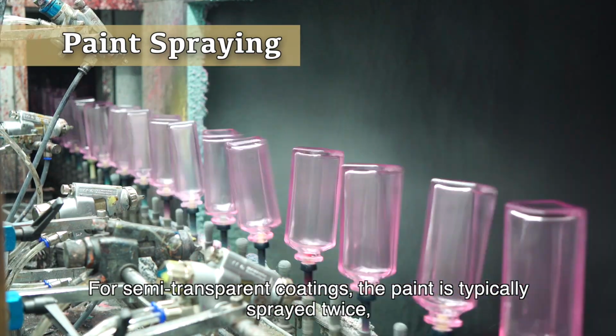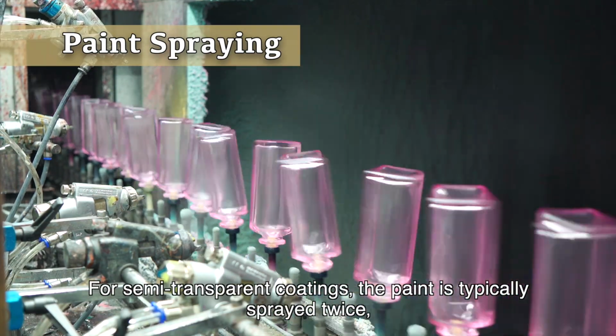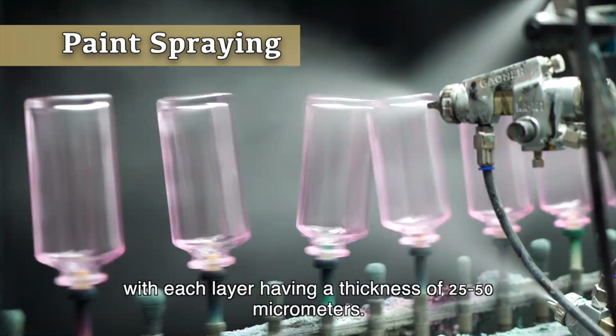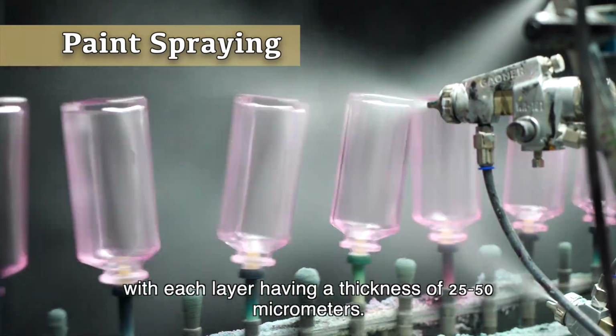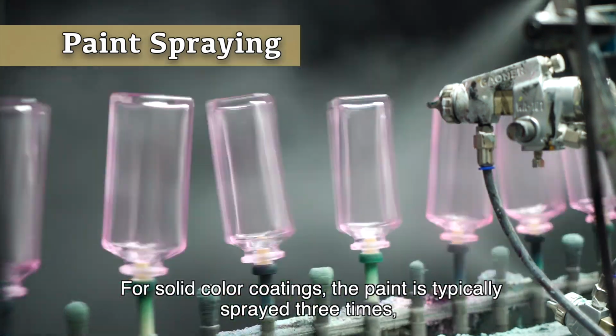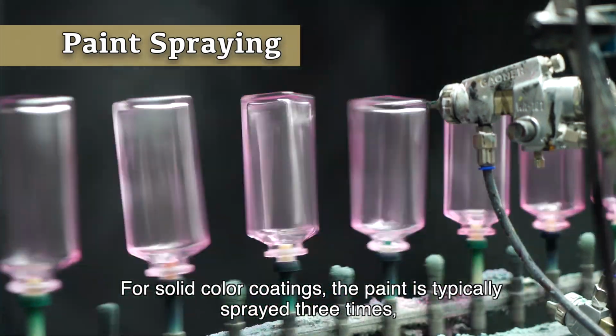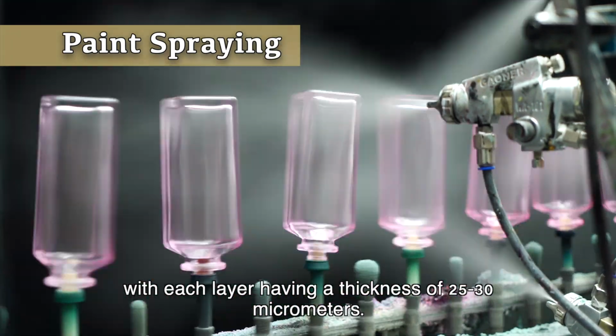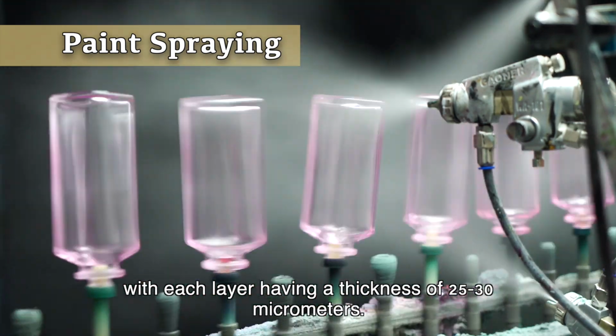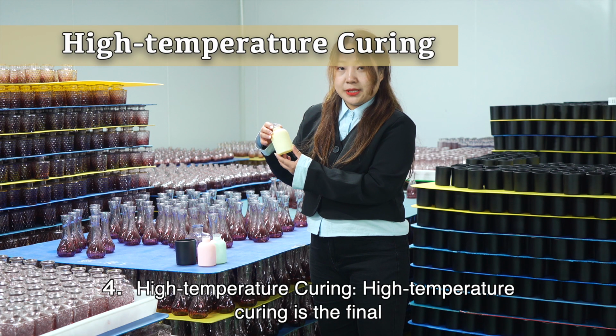For semi-transparent coatings, the paint is typically sprayed twice, with each layer having a thickness of 25 to 50 micrometers. For solid color coatings, the paint is typically sprayed 3 times, with each layer having a thickness of 25 to 30 micrometers. 4. High-temperature curing.